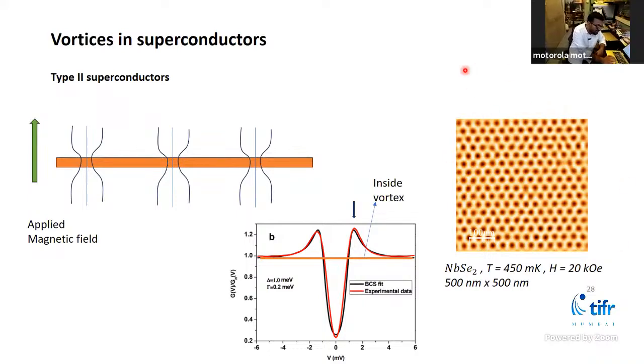So how do we image them using our superconductor? As we have shown you this gap, from where the magnetic flux is passing, our material turns normal. It's no longer a superconductor locally in that region. So there, our conductance is simply flat. It does not vary much with voltage, whereas in the superconductor, the conductance will vary highly. So we fix the voltage between tip and sample to this point, and as there will be a difference in conductance, we record the current, and hence by extension the conductance. So we can see the difference in conductance where a vortex is and where it is not, and that's how we can image them. And you can see a beautiful hexagonal ordered structure formed by the vortices in this material.